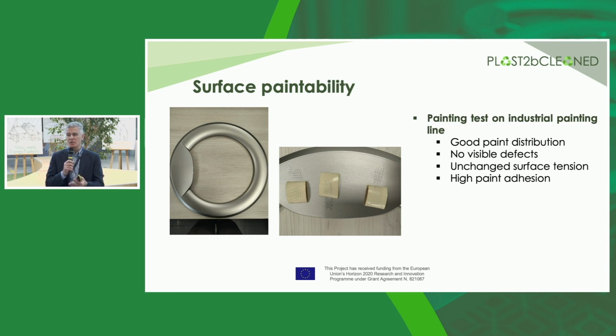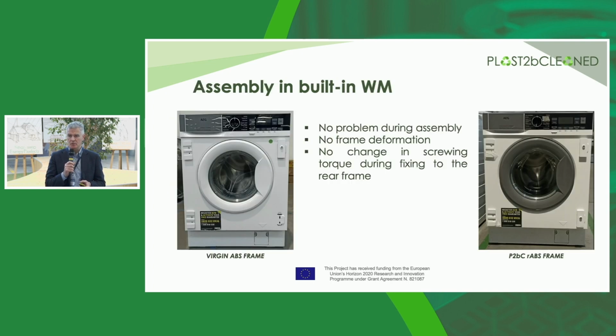So the adhesion of the paint was good, and you can see in the photo on the right side that the typical cross-cut test, cutting the surface and removing with an adhesive tape the paint, was really positive. There was no detachment of the paint. And again, that was a very, very good result.